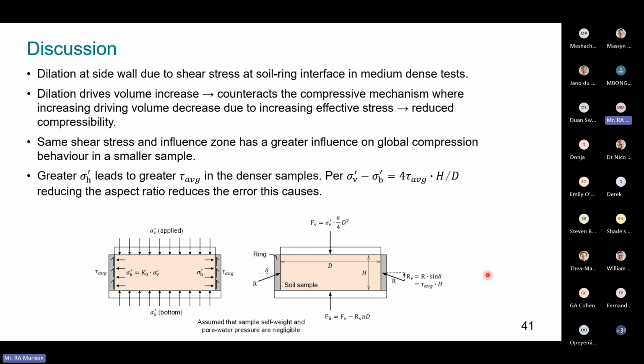So why are we seeing what we're seeing? Well, if we start off with the medium dense samples dry of critical state, any shear stress mobilized along the soil-ring interface would result in dilation. And that's a mechanism which is driving volume increase and counteracting our compressive mechanism through the increase of effective stress. So because of these counteracting mechanisms, we should witness reduced compressibility.